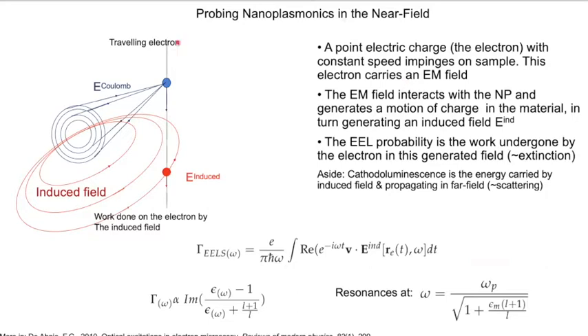And so how we're going to do this in the near field is that we're going to use electron energy loss spectroscopy, and we're going to send in an electron. That electron acts as a point electric charge, and it carries an electromagnetic field. Remember a couple of slides ago, I said if that particle sees an electric field, the electrons will displace. Well, this is what's happening. This electron in your transmission electron microscope is carrying an electromagnetic field, which will induce a polarization in the nanoparticle.